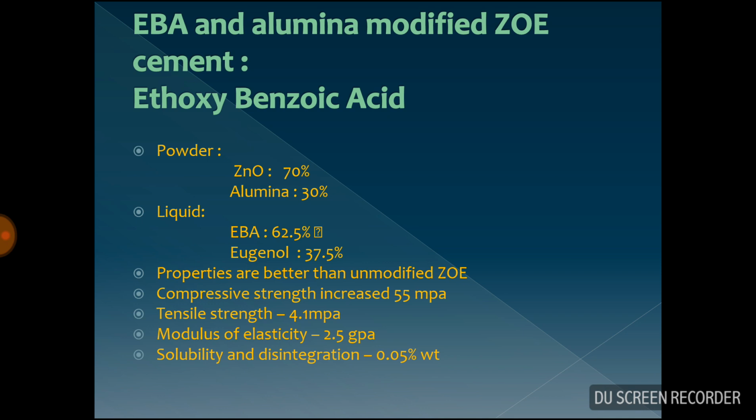The compressive strength is increased to 55 MPa. Tensile strength is 4.1 MPa. The modulus of elasticity is 2.5 GPa. The solubility and disintegration is 0.05% by weight.